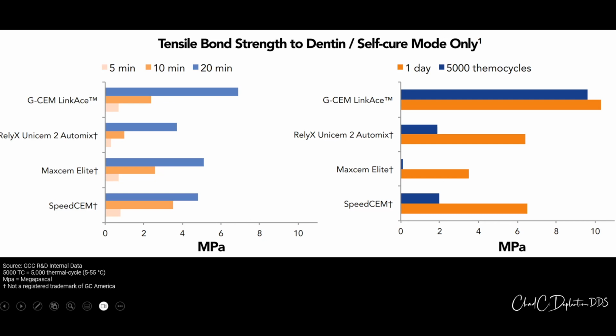One thing that you'll notice is also after 5,000 thermocycles, which is basically similar to simulated chewing or simulated time in the mouth, days in the mouth. After 1 day, you're going to have your maximum, but after several thermocycles or after several days or months or years in the mouth, the tensile bond strength to dentin is going to decrease ever so slightly as well. And that goes across the board.